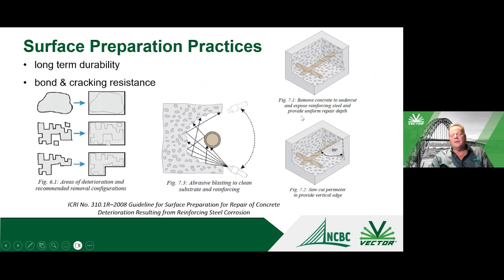concrete removal and effectively the exposure of the reinforcing. So we want to basically chip around the bars and fully expose any bars in the repair area that are corroded, so that you can get the repair material to fully encapsulate the bar. And some materials may claim that they can have a little feather edge. They get kind of thin at the edge, but that's just an area where you can have rapid drying of the repair materials and weak layers.